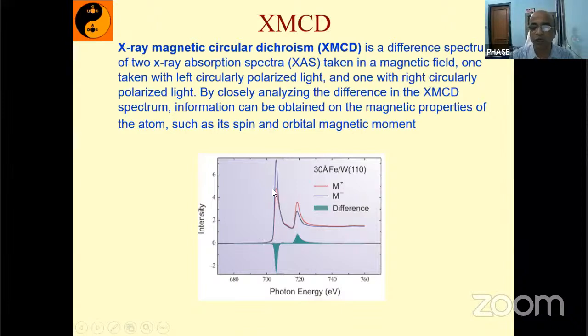One using left circular and one using right circular. There you will get the absorption difference, and that absorption difference basically gives you the XMCD, X-ray magnetic circular dichroism, spectrum. And this X-ray magnetic circular dichroism is useful to study the magnetic properties of the material. It is basically the signature of the magnetic material.